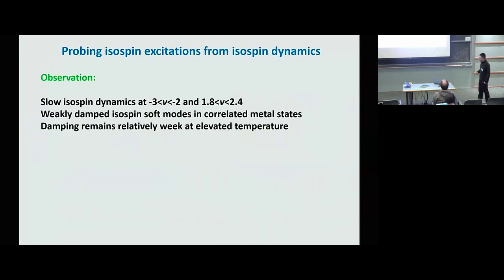Okay, so at the end, let me give a quick summary first. Our main observation is slow isospin dynamics at these 2 regions, in the filling -3 to -2 and 1.8 to 2.4. And the most surprising one is probably the weakly damped isospin soft modes in the metallic state between -3 and -2, which is an interesting region. We also find the damping remains relatively weak at elevated temperatures, which is quite unusual. So we're still working and trying to understand this observation. If you have any idea, please let us know. Any input would be appreciated.